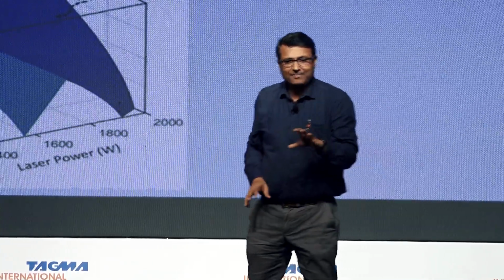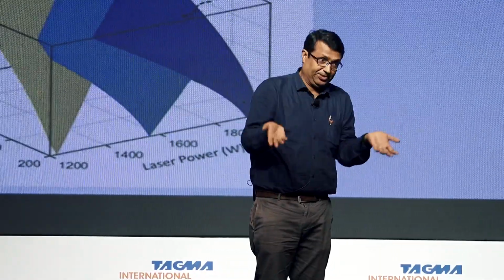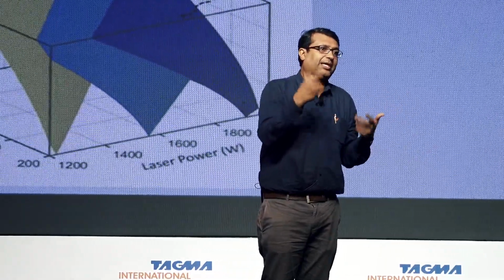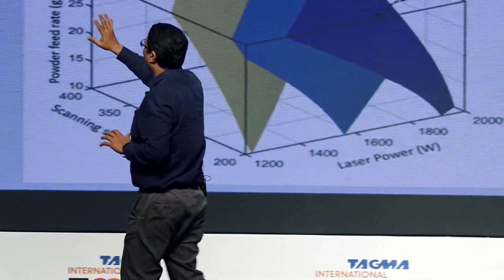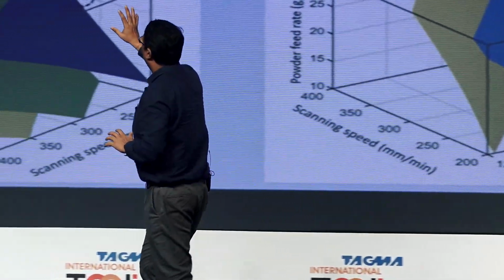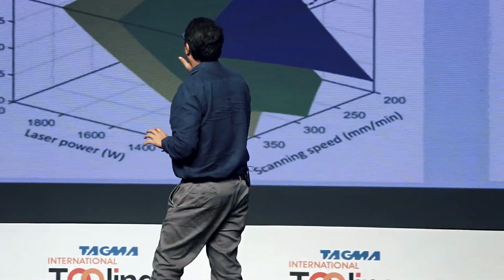So all these three maps: the first map shows this, and for the third map, the entire deposition should be under compression. If there are tensile stresses, the crack can grow and I will not have a good life. So with all these simulations, what we did was, we got process parameters where I will have a good clad.